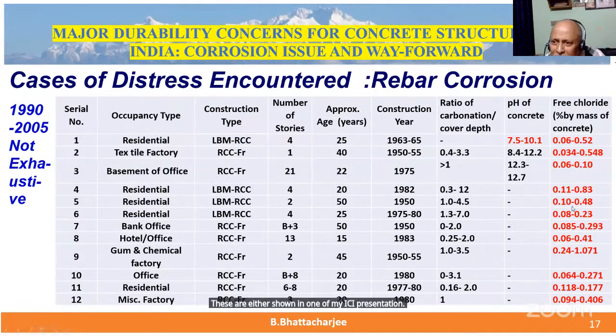And the chloride, water-soluble chlorides, most of them show red because they were relatively high. In some cases pH was low. This, 8.4, is also low. And this was definitely low. Now, generally what happens is where the life was longer, as you shall see, possibly in the bank office, this value was there. But since there was no moisture, there was no problem. But some good bank buildings, 50 years old, had no problem at all.